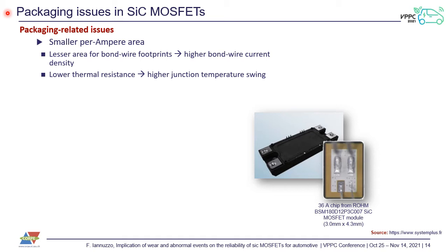All right, let's move to the first one in a little more detail. Packaging issues in silicon carbide MOSFETs. Packaging related issues are basically arising because of an intrinsically smaller per-ampere area. This comes from the fact that thermal conductivity and power dissipation capacity are better than silicon. But together with this, there are two challenges. One is that you have a smaller chip for the same current to manage, which means you have less area for landing bond wires. This turns into a higher per bond wire current, which, as I will show you in a slide, is a very challenging phenomenon.